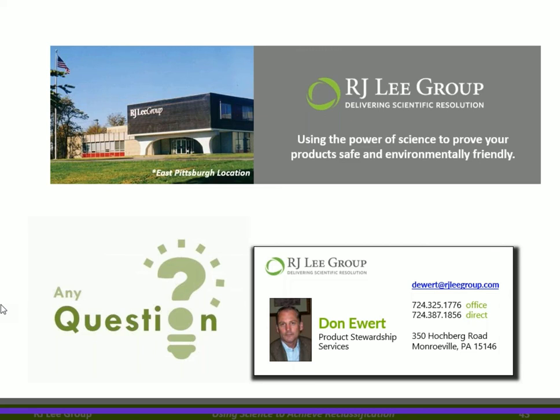There is another one. If both quartz and cristobalite are present in a product, can they be reported on the SDS together under the same CAS number, or must they be listed as separate ingredients? If your cristobalite content is greater than 0.1%, we recommend listing it. And then also looking at whether it's bioavailable, and that's your choice. You'll notice that cristobalite is rarely formed. We do see it in products, but they're always heat-treated products or calcined materials. And generally it's bound. We have not found free cristobalite in any of our work thus far, although we do see it in materials that have been heat-treated.